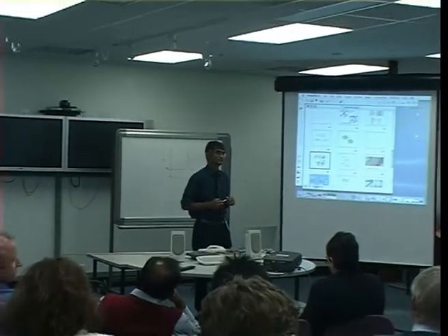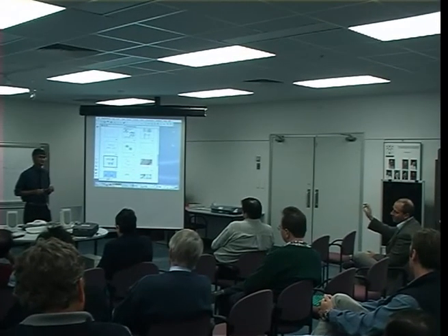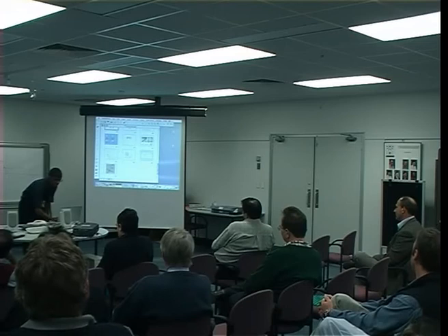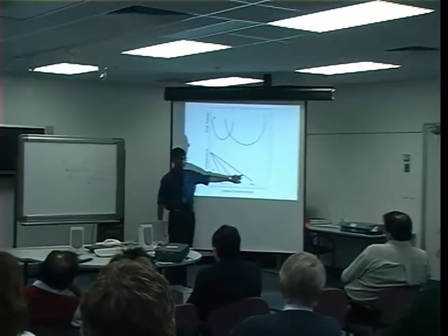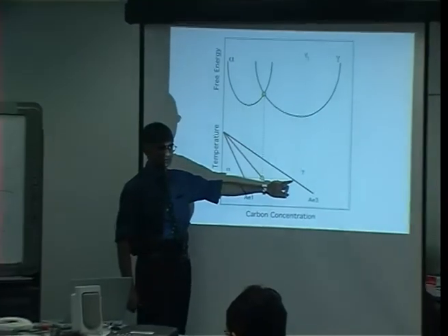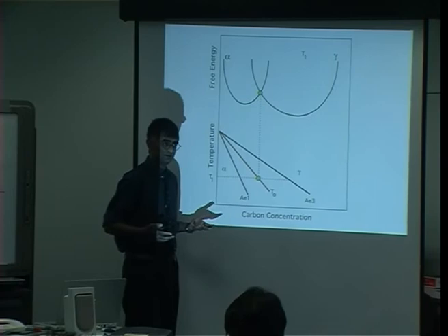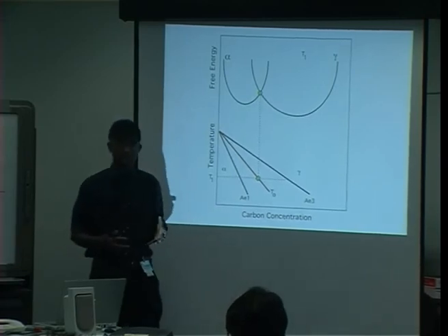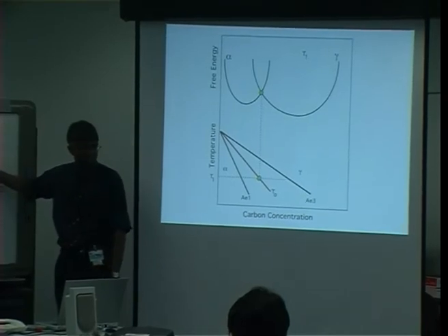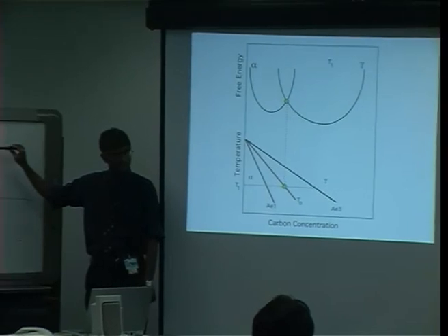Can you also shed a bit more light on a really important factor, the carbon diffusion from the austenite? So again, the driving force, that needs to be in equilibrium? You know what I mean? Yes, I know exactly what you mean. According to this, the solubility of carbon in ferrite is far, far smaller than in austenite, orders of magnitude smaller. So the carbon doesn't want to be in the ferrite. Now, in the case of martensite, it's forced to be there because the kinetics does not actually allow it to partition. And that's why we get these other reactions, which I will come to. And we will develop a theory for diffusion control growth.